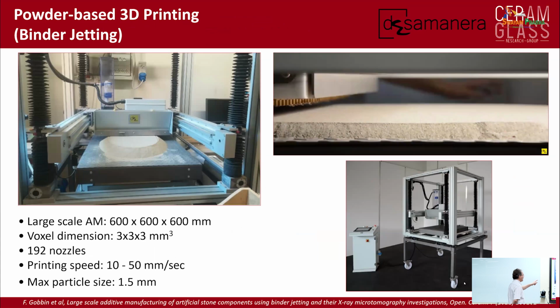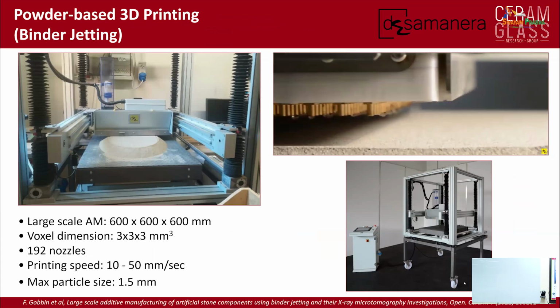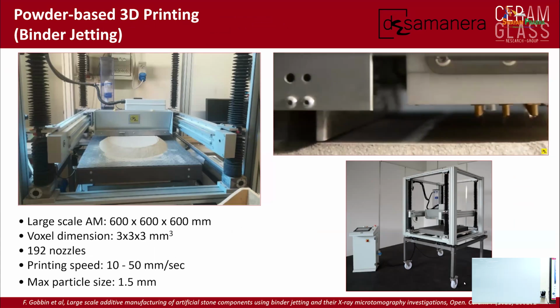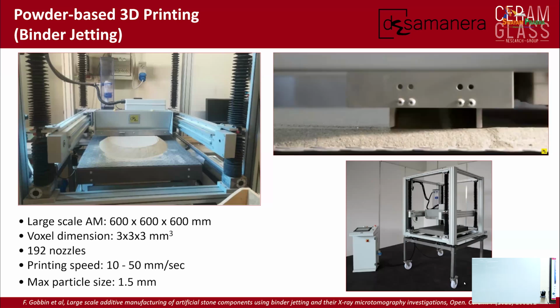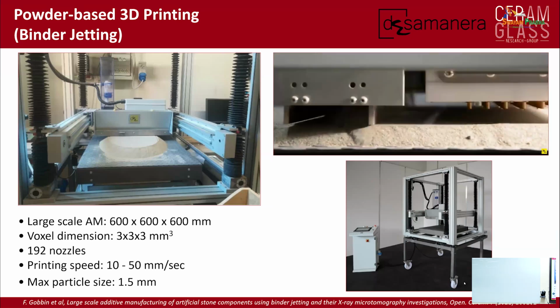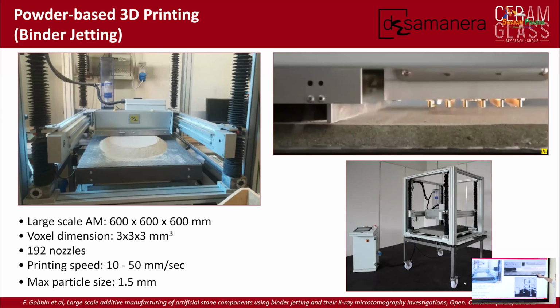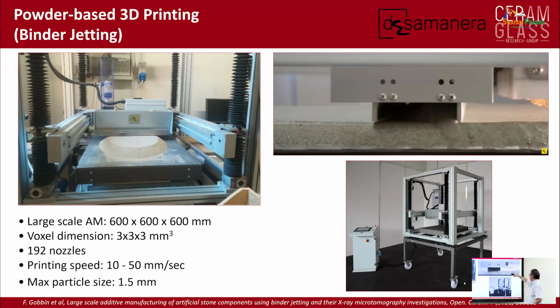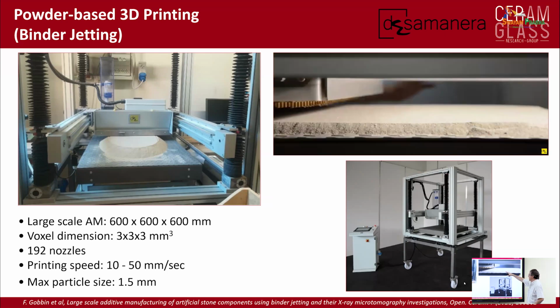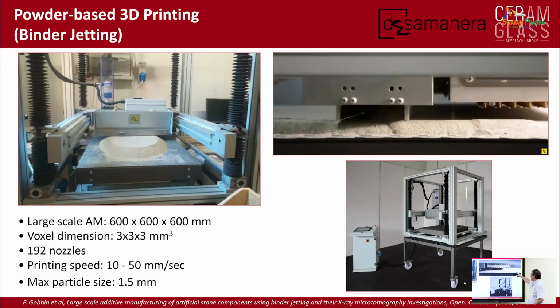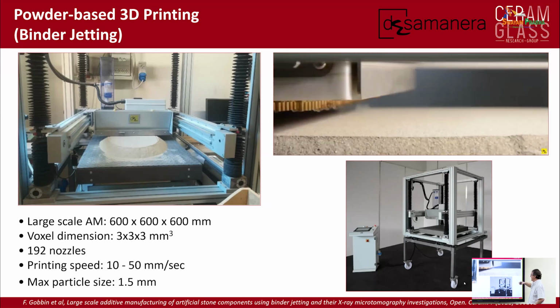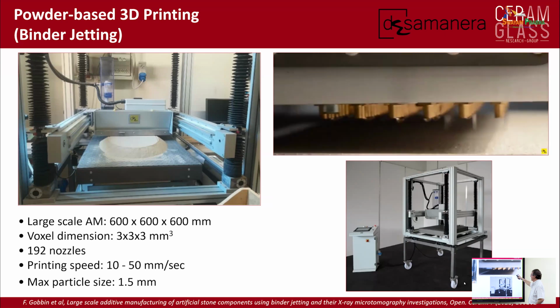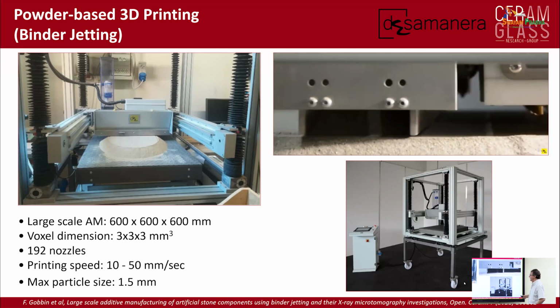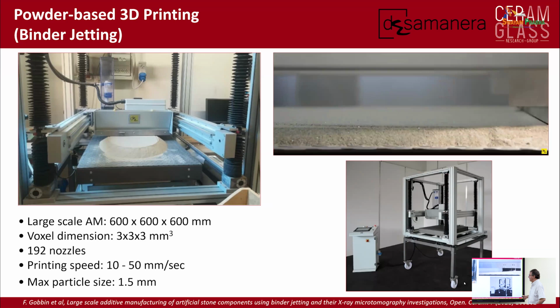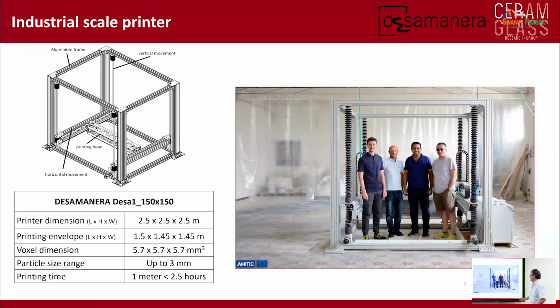So this is our printer. So we can print 60 by 60 by 60. And you can see here the printing head. So this is the powder bed that contains metakaolin. And this is a series of nozzles that are jetting the liquid. And you can see also the speed at which this operates. So it's a very effective approach. This is the large scale printer.